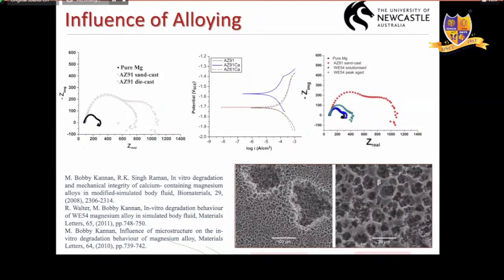And the second one is the die-cast alloy. Here, although it is an aluminum zinc magnesium alloy, the picture you're seeing is mainly an intermetallic. The magnesium is dissolved and left behind this skeletal structure of beta phase. We call it secondary phase particles. What is secondary phase particles? When an alloy is made and reaches a solubility limit, it forms a compound called an intermetallic. In this case, it's a magnesium aluminum intermetallic.